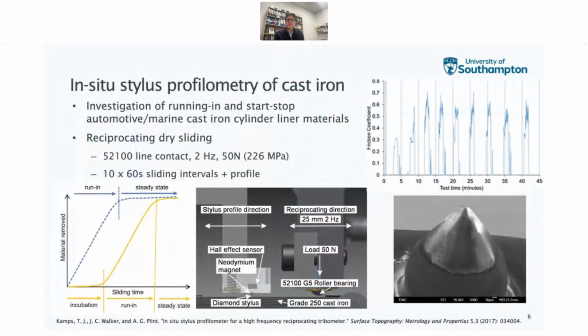So something else we attempted a couple of years ago was to see if, whilst we're doing these sorts of tests, we can actually measure the wear online or in situ without having to remove the coupon and do it gravimetrically or with some profilometry technique. And so we developed a little technique where we could use a diamond stylus to probe the surface after sliding had commenced and measure the profile there to see what the wear rate was.